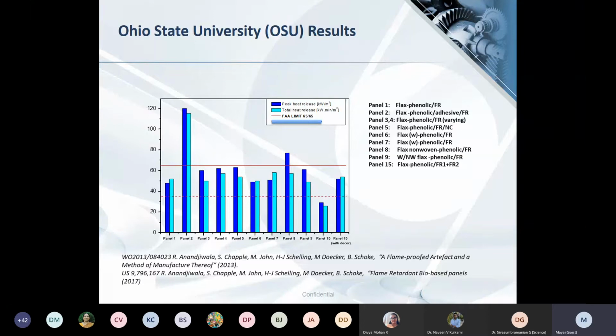So the primary flame retardant treatment was on the flax fabric, while the secondary flame retardant treatment was added into the resin in certain cases, and in certain cases it was added as a coating onto the panel after the panel was taken out of the compression molding press. And you can see that most of the panels are below the 65 limit of FAA, and panel 15, which comprises of two types of flame retardant treatments, shows the minimum value for both PHR and THR.